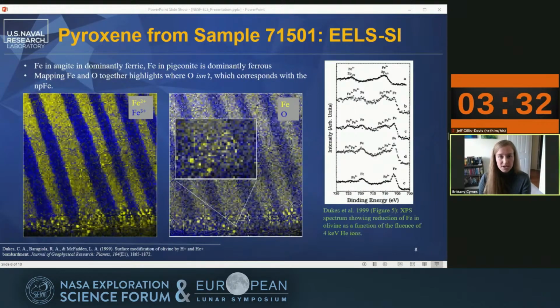And using concurrent standards for iron, we can actually generate maps of multiple oxidation states from these spectrum images to have a better spatial idea of what's going on. And it's very clear here on the left that the pigeonite lamellae host dominantly iron 2 and the augite host dominantly iron 3. And when we map all the iron together with oxygen here in the center, you can see that the iron nanoparticles are indeed reduced as they anti-correlate with oxygen. So we think that this iron valency partitioning is likely the reason why different nanophase iron development is observed.